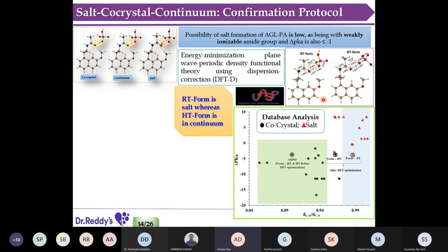So what we did was a simple study. We calculated the pKa of all these things, and plotted the CO by CN distance. If you can see this, that's a big indication, because if the proton gets transferred and the oxygen gets protonated, then the resonance structure will change, and practically the CO distance will be more for the salt as compared to the co-crystals. And of course the CN distance will be a bit less. So CO by CN is a very good indicator of having a salt or co-crystal.